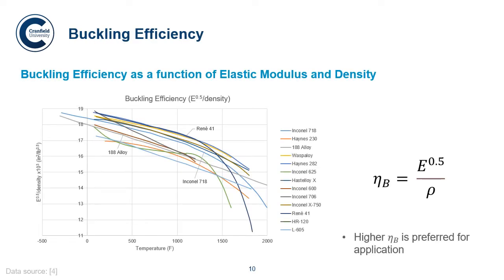Then we also looked at buckling efficiency, which we defined as a function of elastic modulus and density. So a higher buckling efficiency is preferred as well. As you can see, it's a very similar story. We have Rene 41 coming out at the top, Inconel 718 not far behind, but not quite as good at the intermediate temperatures. It's more of a middle ground in this comparison. And then 188 is very constant throughout.